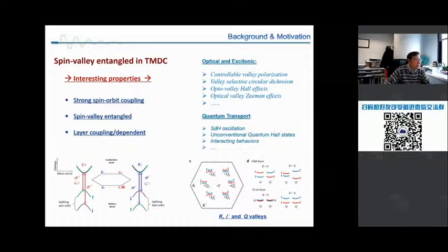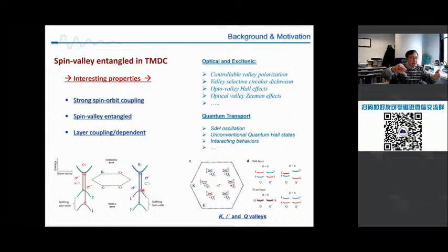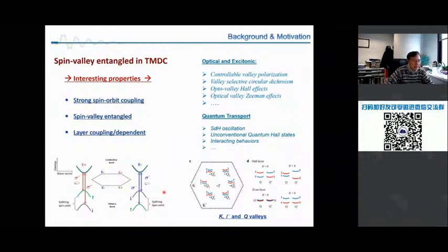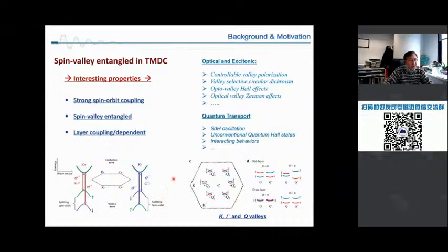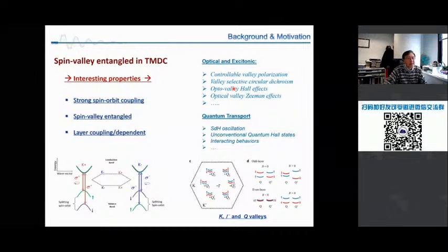So what do I mean? That means because of the time reversal symmetry, these K and K prime valleys are degenerate. And at the lower energy states, the spin up and spin down occupy K and K prime. Right? So you have valley-degenerate states, but they have opposite spin polarizations. Now that gives rise to interesting properties that people use to study this kind of material, such as controllable valley polarization or valley-selective circular dichroism. It is a polarizer and detects the light emitted from different bands.